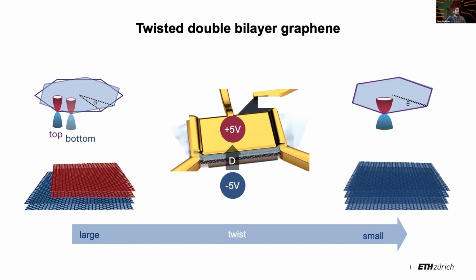Now let's look at the measurement. So this captures rather well what we also see here. So the conductance has peaks at a certain voltage here, and then goes down to something resistive, and this rather symmetric bias here. And this really happens at zero density and at a very large displacement field. So this is also consistent, at least, with the picture that a correlated state is formed, which pushes out electrons from this intermediate gapped region.